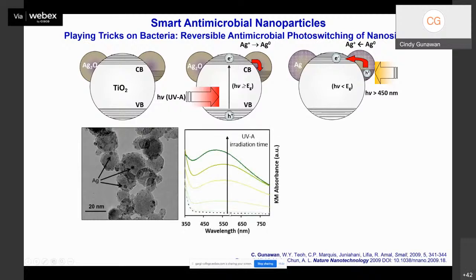And as you can see here, with increasing UVA irradiation time, you could see a more prominent presence of surface plasmon resonance, or SPR, between 450 and 550 nanometers, which is a characteristic of nanometallic silver. So this occurrence of surface plasmon resonance, this hump here, confirms that the silver 1 deposits have been reduced to metallic silver. Now the silver 1 has been converted to metallic silver.